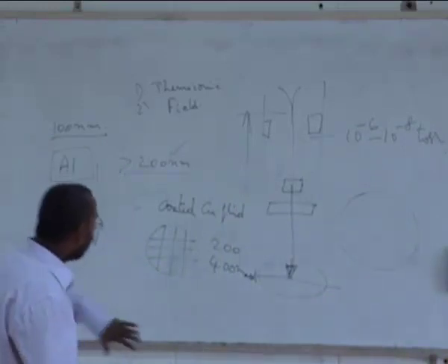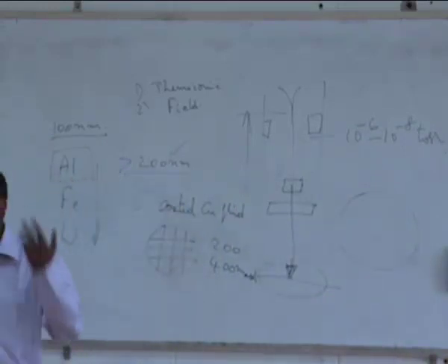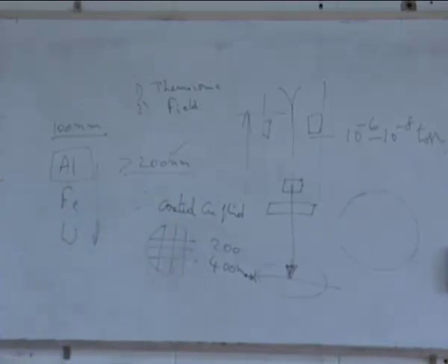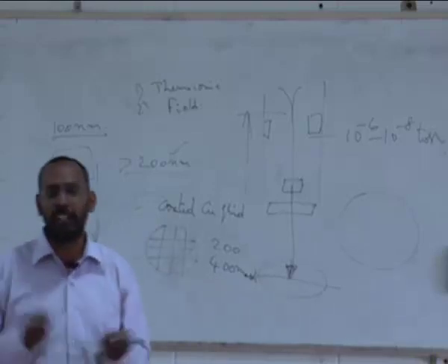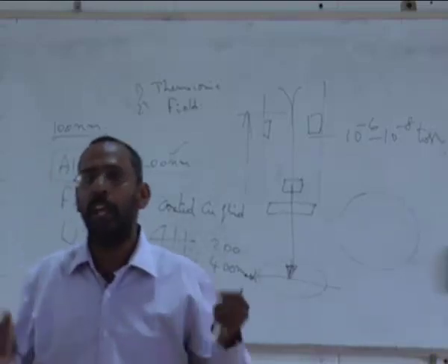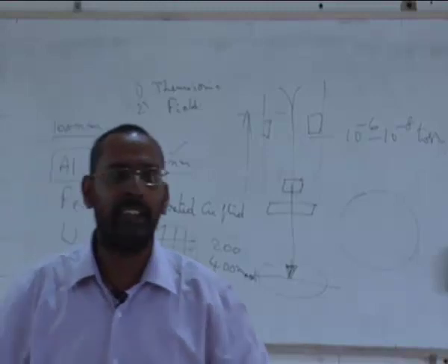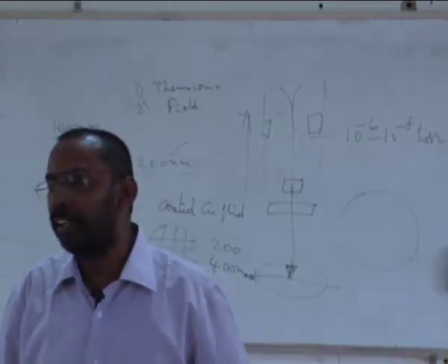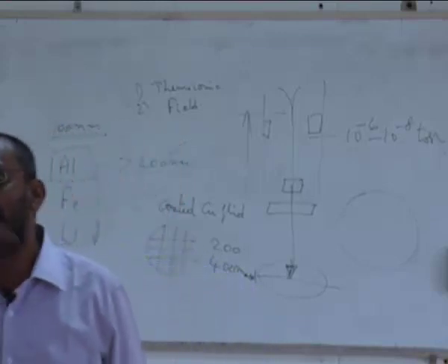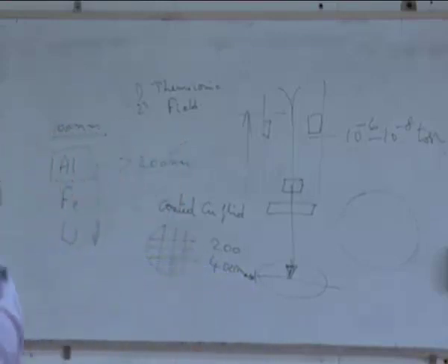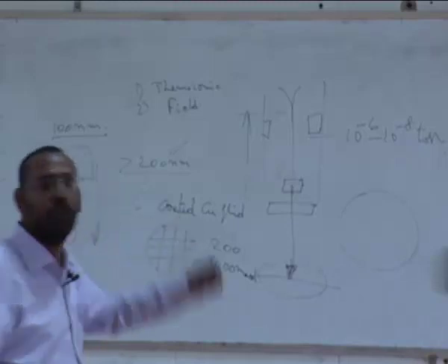So now if I have an amorphous carbon, I will tell you a little later why we use amorphous carbon. If I am putting my nanoparticles on this, what I do is I take the nanoparticles, disperse them into a medium such as acetone, and once it is dispersed, take a drop of this acetone containing these nanoparticles and put this drop on this carbon coated copper grid.